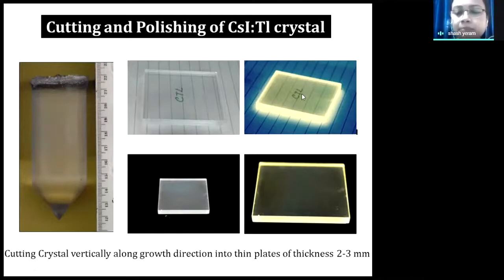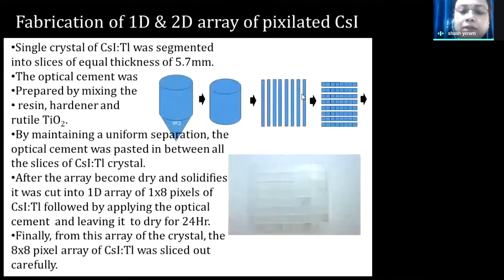So we are making these crystal plates. For the plate I have shown earlier that mosaic crystal. But when we are making a segmented detector, we have to have either a 2D matrix or a 1D matrix. So the crystal which we have grown, cesium iodide, first has to be cut. We make it into cylinders, then slice it in one direction, then rotate it and slice it in another direction. Also, to prevent any crosstalk from one pixel to another pixel, we have to put reflectors, and then do full packaging.